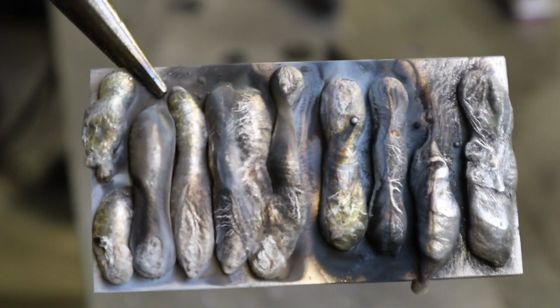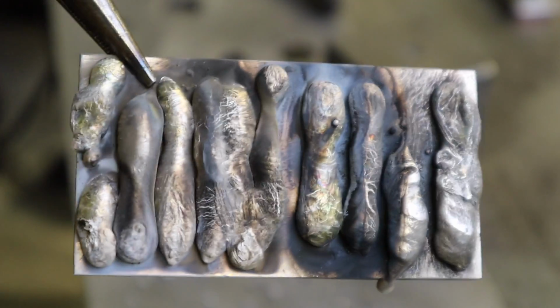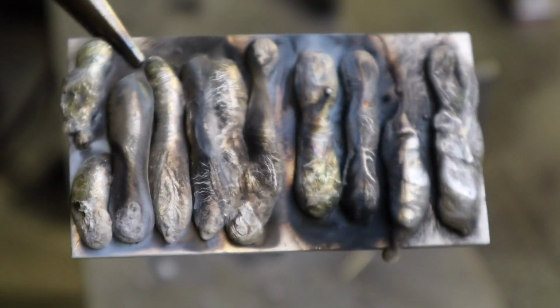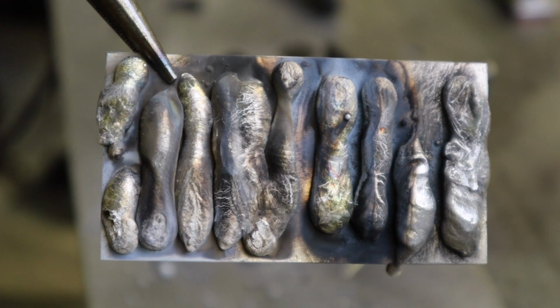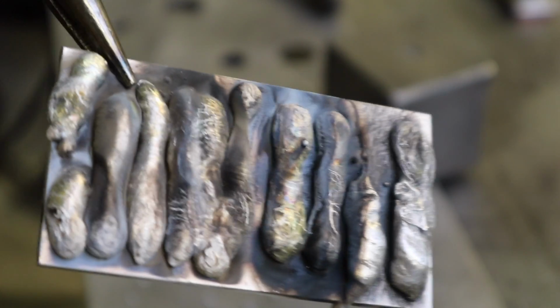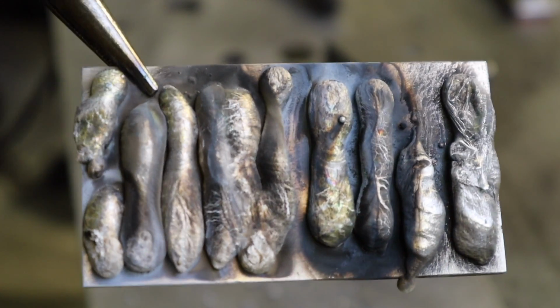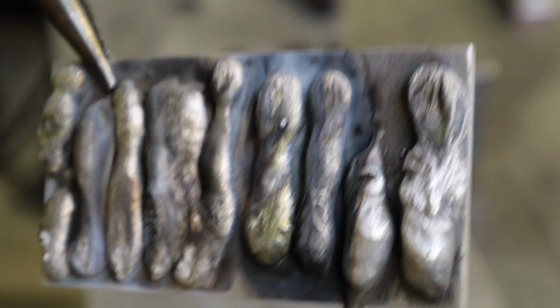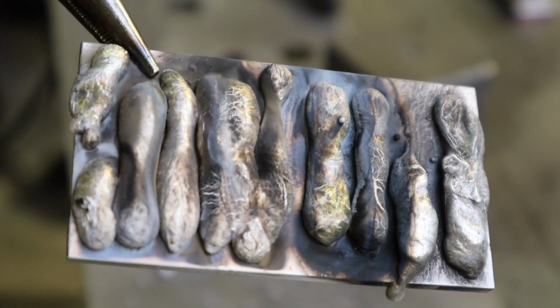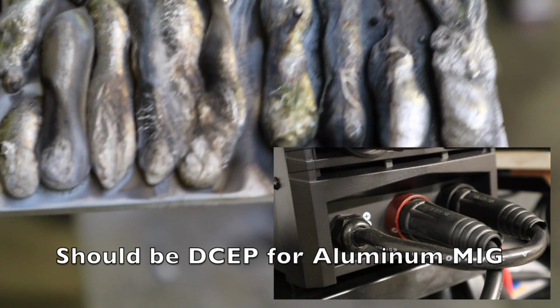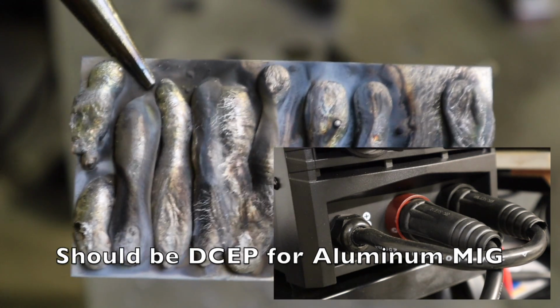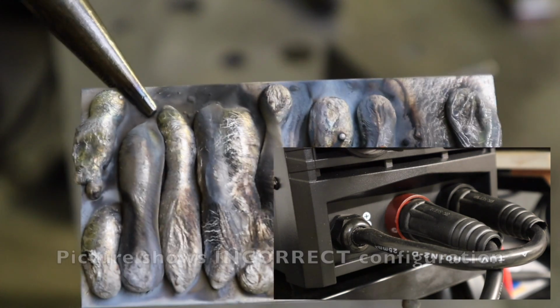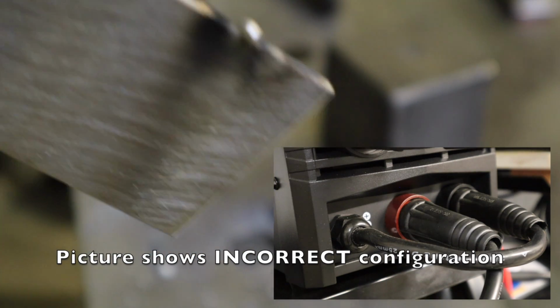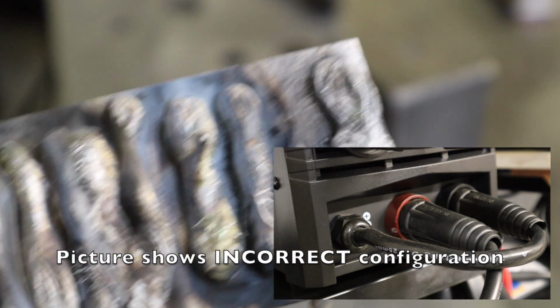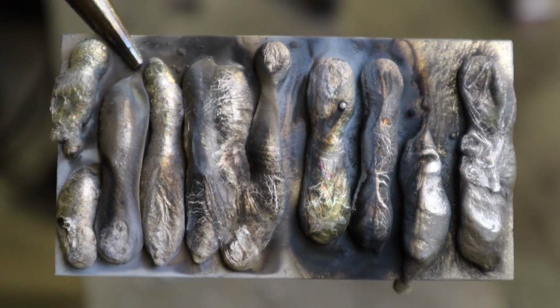I switched from the Synergic setting on the YesWelder over to the manual settings and tried a few settings there. And I was still getting the same result of a bead that was just sitting right on top of the material. And then it finally occurred to me that the polarity was set up incorrectly. I actually, for these first few beads, had it set with DCEN, electrode negative, which is incorrect for MIG welding aluminum. It won't break off the oxide layer if you have it set up like that, and you won't get any penetration. And these are what your beads will look like if you have the incorrect polarity set on your machine.